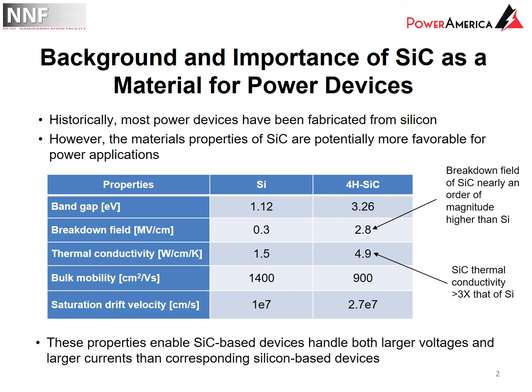Silicon carbide has been found to be a very important material for power devices. Although historically most power devices have been fabricated from silicon, the materials properties of silicon carbide are potentially more favorable for power applications. Specifically, the breakdown field of silicon carbide is nearly an order of magnitude higher than that of silicon, and its thermal conductivity is 3 times that of silicon. So these properties do enable silicon carbide-based devices to handle both larger voltages and larger currents than corresponding silicon-based devices.